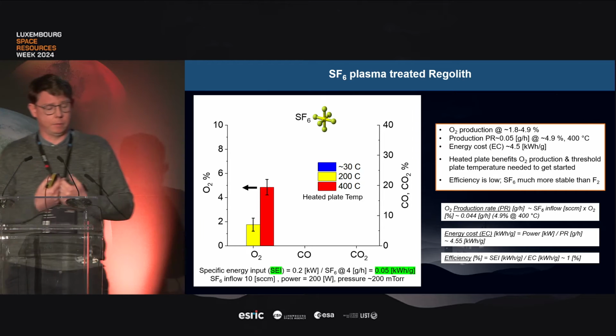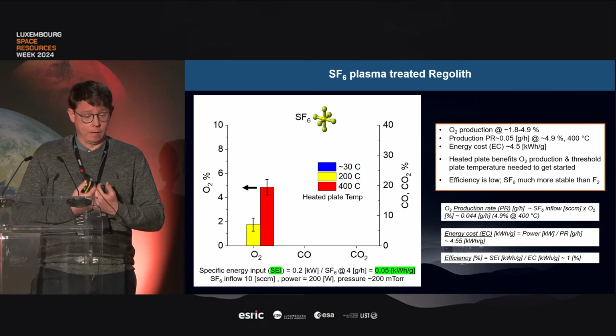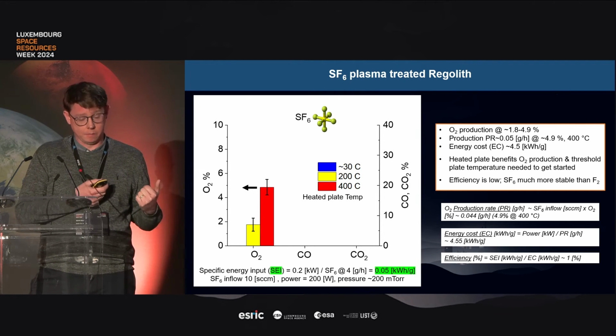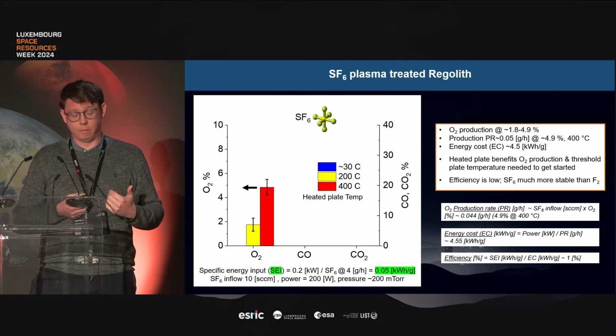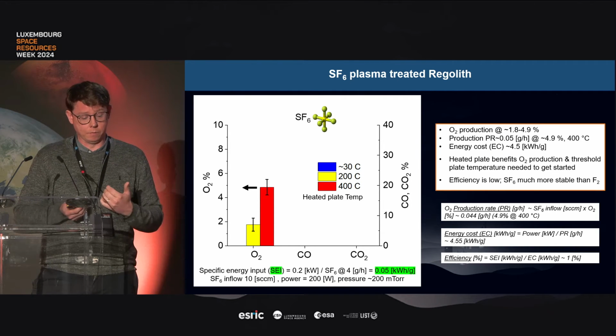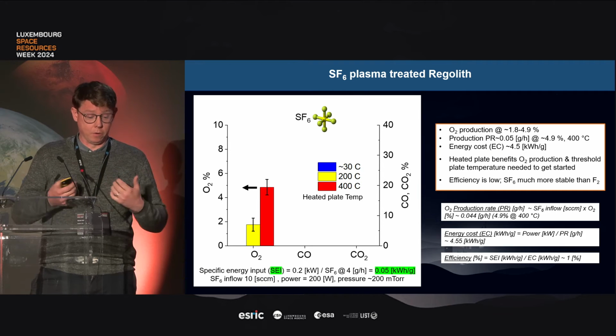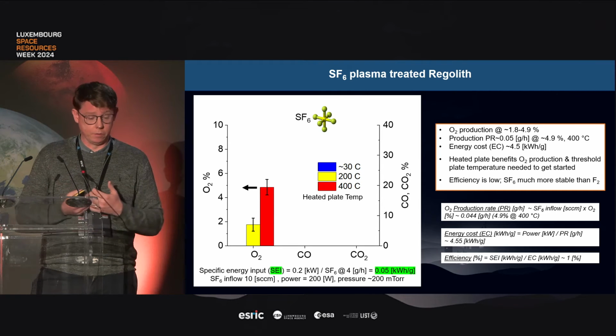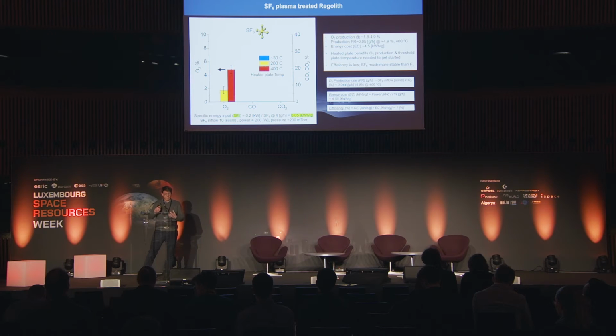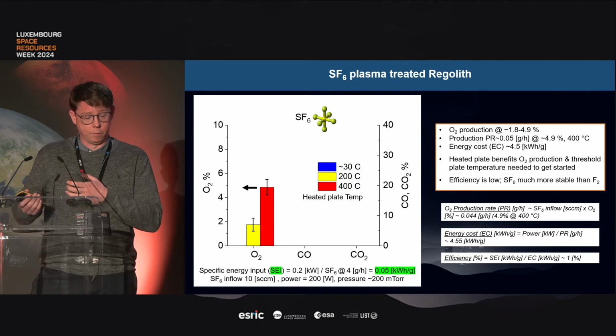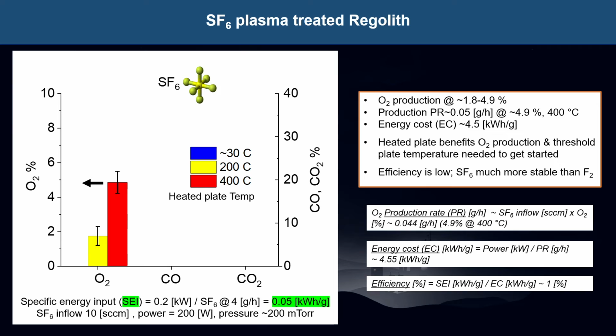So here's the first gas that we treated our regolith with, and this is SF6. First of all, on the left-hand side, just to say the conditions that were used, these are typical for this reactor. We're using about 10 sccm of mass flow, power of the order 200 watts, pressures of around 0.2 torr. In order to get an idea of the metrics involved of the energy, of course this is not optimized, it's just an exploratory study. I've calculated the specific energy input. So it's the order of 50 watt-hours per gram of gas, and we're only flowing about 4 grams of gas per hour of SF6. So on the right here, we can see some of the production values.